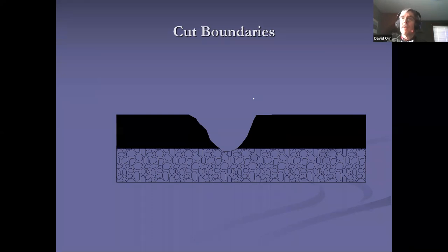You need to look at the pavement. I will be honest with you, there are sometimes you look at it and you realize I've got to go even a little bit further. While it's not quote unquote cracked, it's in pretty sad shape. But generally these edges, even if you can't see them, there are little micro cracks in here, okay? So I would go minimum 6 and preferably a foot, okay? You're not going to spend that much extra on material, and you're really going to do a good job of cleaning up and making sure you get to good solid material. So that's pretty important. You want to definitely do that.